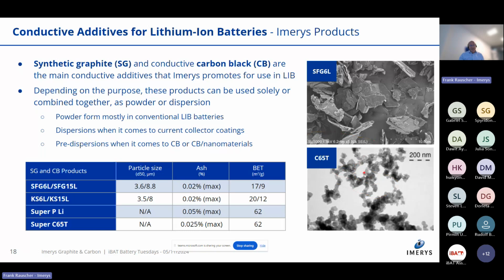This is a very different material, as you can see here. Look at the scale, it's 200 nanometers. So the primary particle size here is between 20 to 40 nanometers, depending on what type of carbon black we look at. And those primary particles are agglomerated, grown together. And what you want is a highly structured, three-dimensional carbon black particle, because that's what provides conductivity.